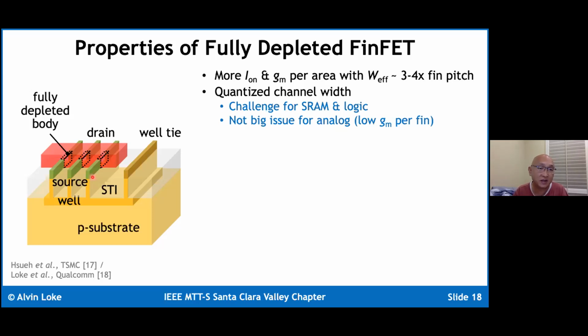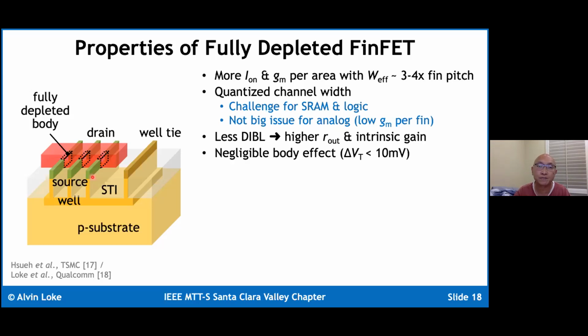Okay, in FinFET for analog, it's not a particularly big issue to have these quantized channel widths, largely because the GM per fin is pretty small. It's in the order of 10 to 100 microsiemens. Okay, and we're typically going after, conventionally, in the order of 1 millisiemens type numbers for typical analog circuits, so you need many fins to accomplish that. So the quantization of the channel width is really not as big of a problem in analog. I'd mentioned lower DIBL, which means that you have higher R out and intrinsic gain for a given channel length.